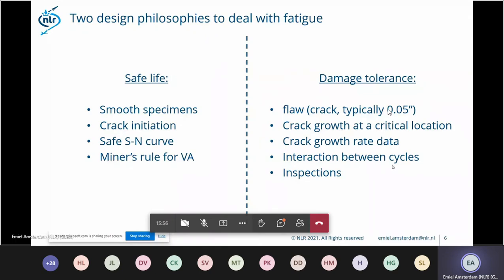So already at the beginning of the 70s, they came up with a damage tolerance design philosophy, where they assume that there is a flaw already present in the material and in the structure, and that it grows at a critical location. They use crack growth data to determine the life, and interaction between high and low amplitude cycles to deal with variable amplitude fatigue, and the safety is guaranteed by inspection. So it's also called safety by inspection. That's the damage tolerance approach. So one deals with crack growth, and the other, safe life, deals with crack initiation. Those two are quite separate in design of fatigue.